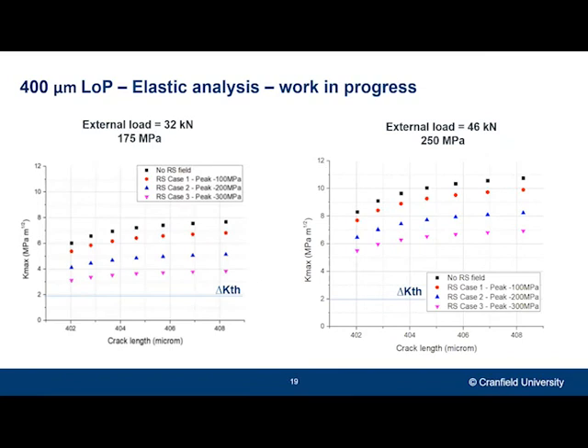Now, this is also a work in progress, but here you can see the effect that different residual stress fields have on the stress intensity factor of the crack. There are two different load cases, 32 and 46 kilonewton. And for each load case, the defect was surrounded by different stress fields. So there's a case with no residual stress fields applied, which is the one in black. And then there's cases going from 100 to 300 megapascal peak compressive stress. And as expected, the bigger the compressive residual stress field is, the smaller the stress intensity factor will be.